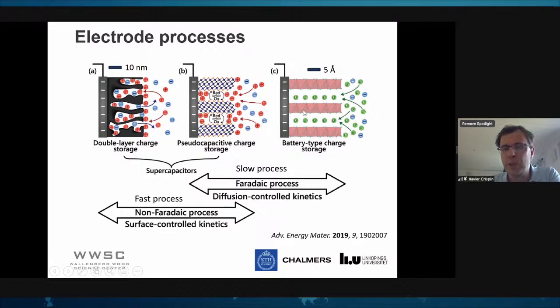and Faradaic process in which the material itself undergoes a redox reaction. If you have a redox reaction, it typically occurs at a very specific potential. So you will see a plateau or feature in the electrical characteristic at a certain potential, while in the electric double layer you don't have any specific feature. You're just charging a conductor more or less by this electric double layer. It does not depend on the potential. I mean, the more potential you apply, the larger the charge you put, but there is no specific threshold of any kind, because there is no redox reaction, there is no electrochemistry going on.